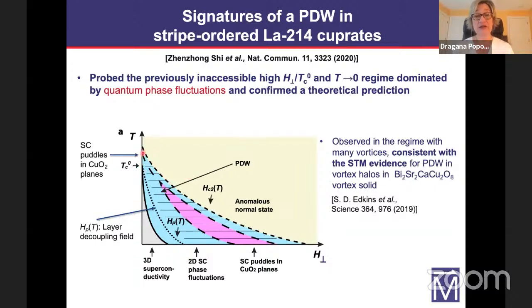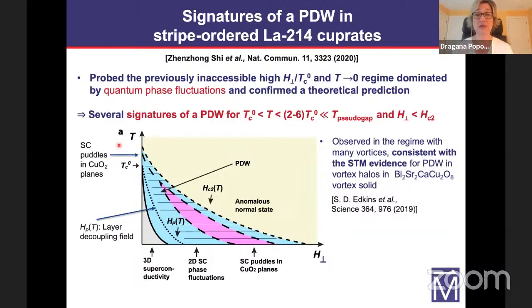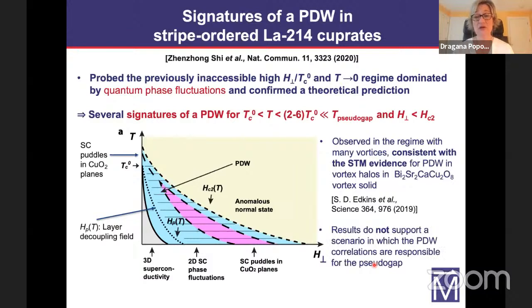The extent of the observation of the effect of the parallel field, or the evidence for pair density wave, extends to temperatures that are several times higher than Tc, basically up to temperatures where we see the onset of phase fluctuations. And as I said before, this is a much lower temperature in these materials than the pseudogap temperature. And we also do not see any evidence for a pair density wave for fields that are higher than the critical field. So our results do not support a scenario in which the pair density wave correlations are responsible for the pseudogap.